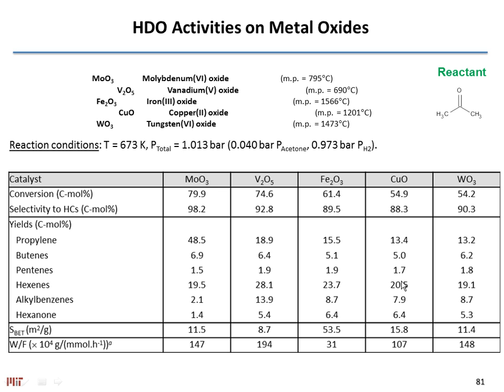So we have molybdenum, vanadium, iron, and from there we see that molybdenum gave us some very interesting results for acetone HDO chemistry. We actually produced quite a bit of propylene, and then we saw hexenes that came from the HDO of the coupling product of acetone, for example, mesityl oxide in this case. The rates were good. All the other catalysts also worked, but not as well as molybdenum oxide.